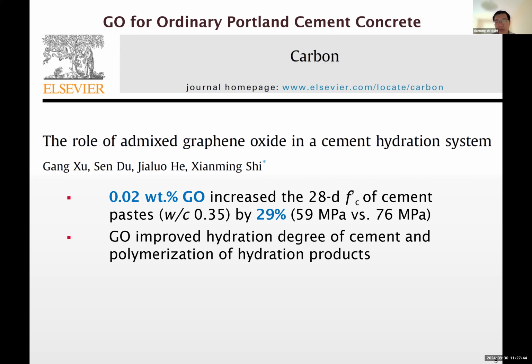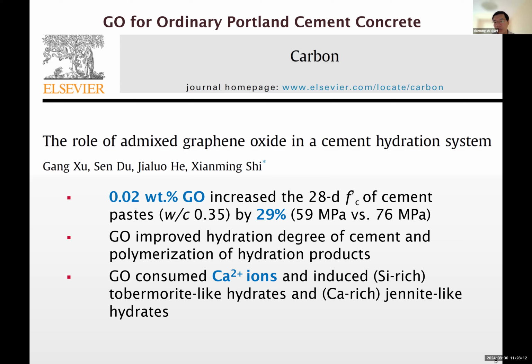focuses on the fundamentals. So it's not a real concrete system, it's a cement paste. You can see 0.02% increases the 28-day compressive strength of the paste by about 29%. On the mechanism side, we reveal that the graphene oxide is more than just a nanofiller. It improved the hydration degree of cement and the polymerization of these hydration products. Also, because they're negatively charged on the surface, imagine really strong, mechanically strong, and even thermally, well, I take back the thermal part. The thermal part is, if we reduce the graphene oxide, removing some of the functional groups, then we can make it thermally and electrically conductive.